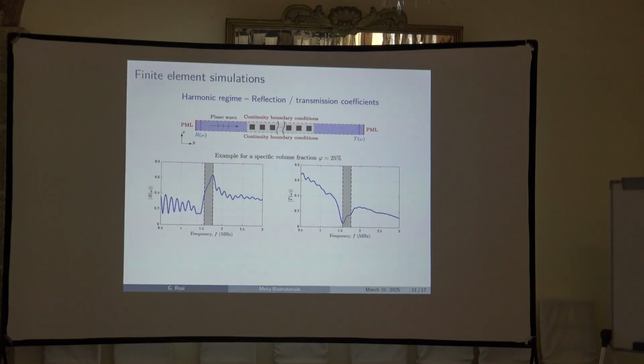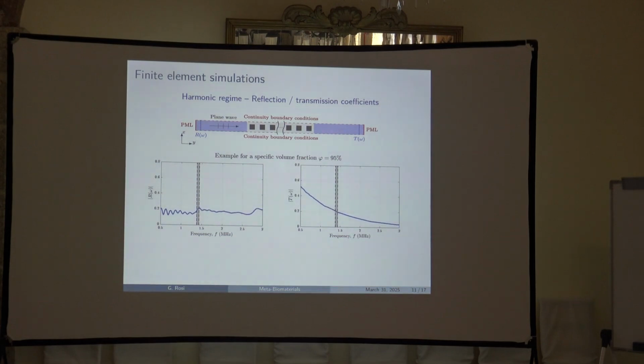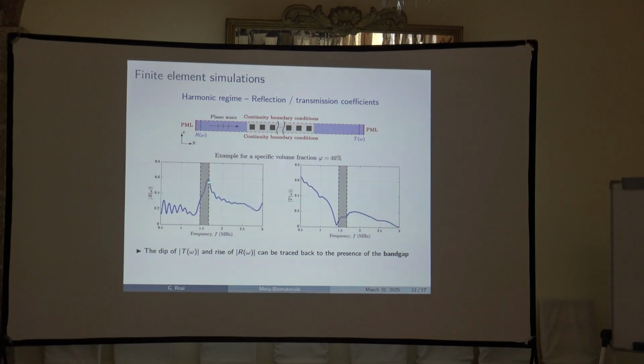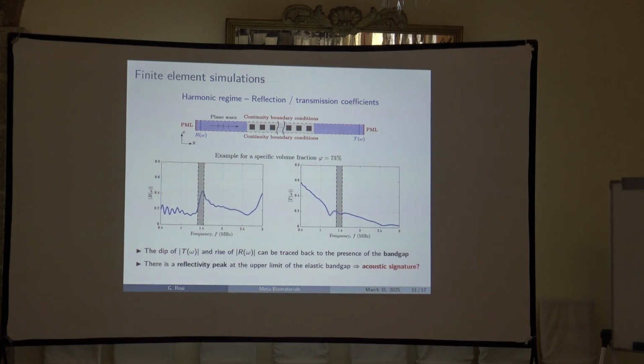So the result for one given volume fraction is this one, reflection coefficient, transmission coefficient. You have a drop of the transmission coefficient as it is expected when you enter the bandgap, and you also have a peak of the reflection coefficient when you enter the bandgap. We played with the volume fraction, and you see an evolution of the bandgap, and basically what you can observe already is that this peak in the reflection coefficient always follows the end of the bandgap, and this is what we will try to exploit as an acoustic signature.